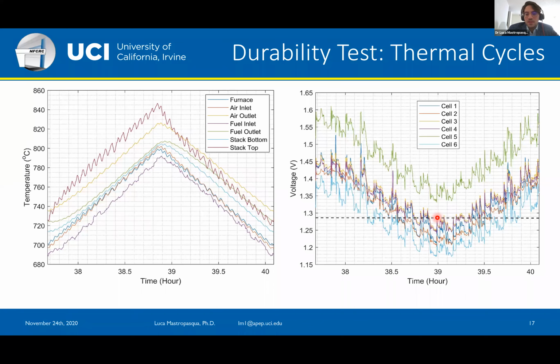fluctuating, let's say. And another interesting thing that highlights the complication in terms of heat management of these systems is that the dashed line here is the limit between the endothermic region below the dashed line and the exothermic region above the dashed line. So you can see that, for example, there are some cells that operate endothermically, and in this case, one cell that operates exothermically. So the challenge in a real system would then be to design again a really good control system that maintains the temperatures in the stack